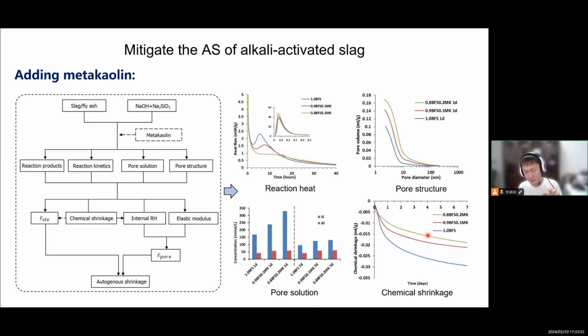But in the later age, because of the reduced reaction rate, the total chemical shrinkage becomes lower, which means there will be less water consumption and less self-desiccation. But the strength is still similar, which is good news, because it can reduce the shrinkage but maintain the strength. Although the mechanism is not what I thought in the beginning, it still worked.